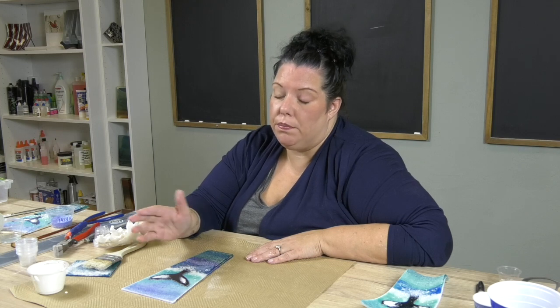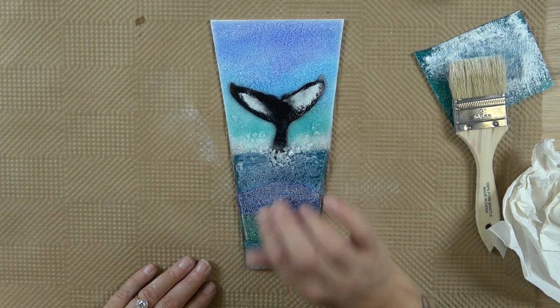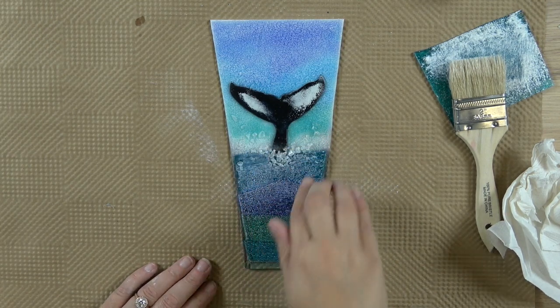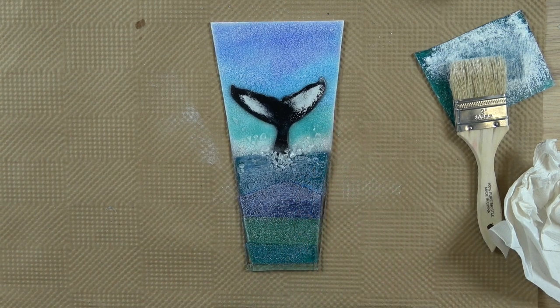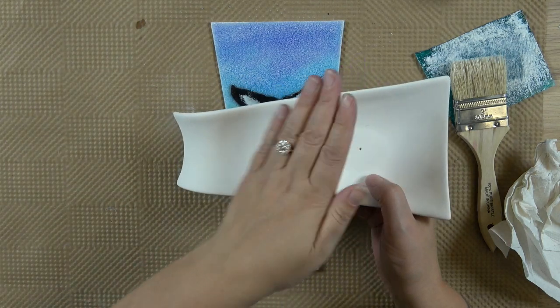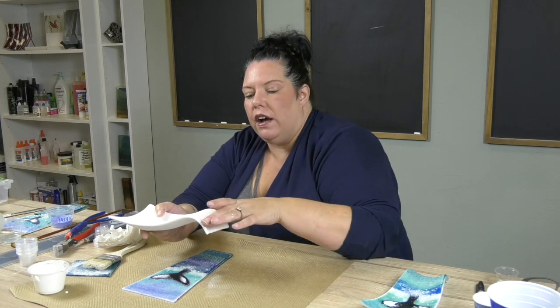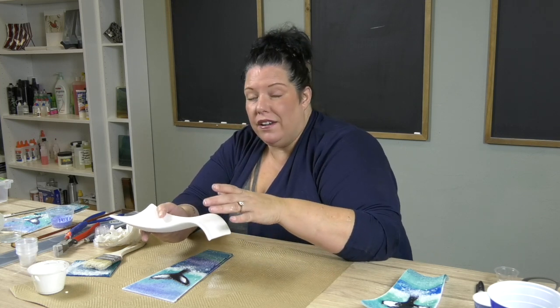Guys, you could take a diamond hand pad to it, but I slump very low to get over that big hump of the mold. Very, very low. If you're looking where my eyes are going, there's this awkward hump right there. So I go very, very low, like 1160, and I hold for a long time, super low, but I get perfect slumps, okay? Now, that's not enough. If you start grinding this thing, it's not enough to take out those grinder marks at 1160.